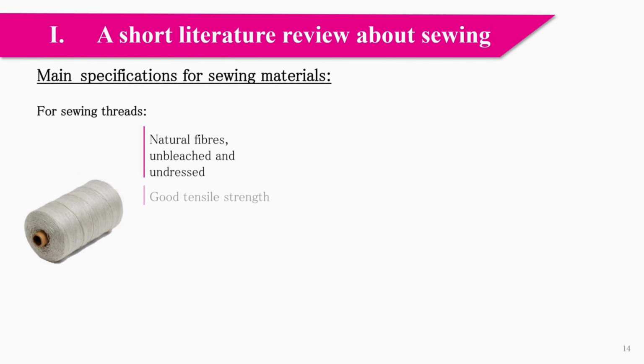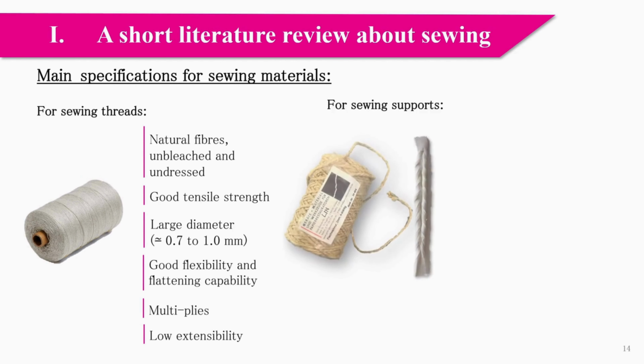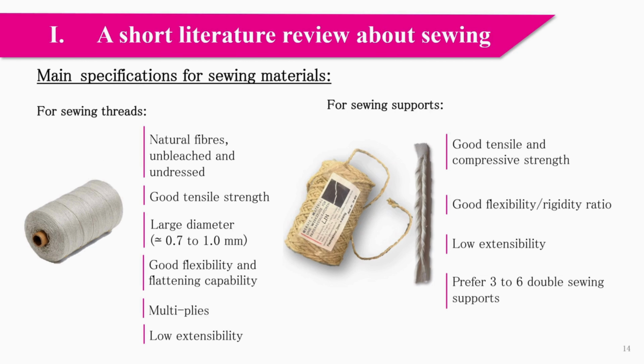According to the literature and conservation ethics, the sewing support and threads must be chemically and mechanically compatible with the original materials. That means for sewing threads, natural, unbleached and undressed fibers to meet the ethics in terms of chemical compatibility and aging. Also a good tensile strength, large diameter to limit the risk of tearing in the center fold of the signature during the sewing, sufficient flexibility and flattening capability during the sewing, multiple plies and low extensibility.